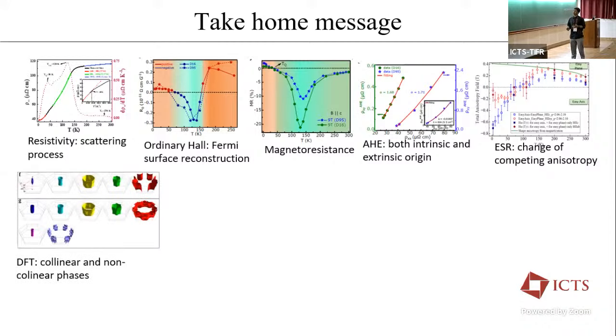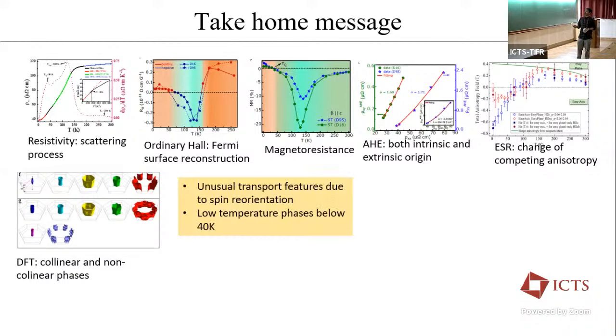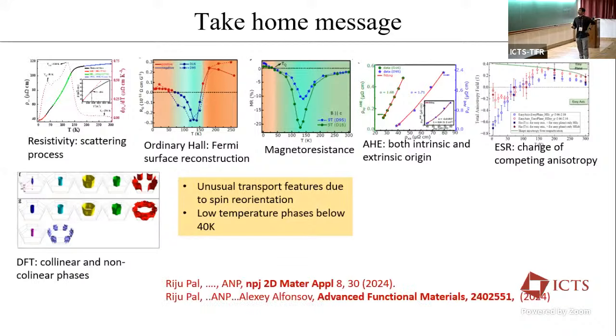And then the DFT calculation at least shows that two phases are possible in this material, which may be the spin reorientation driven phase. One is the spin reorientation driven phase, and another is the collinear phase. With this, these are the main observations: unusual transport features due to spin orientation and low temperature phases below 40 Kelvin.